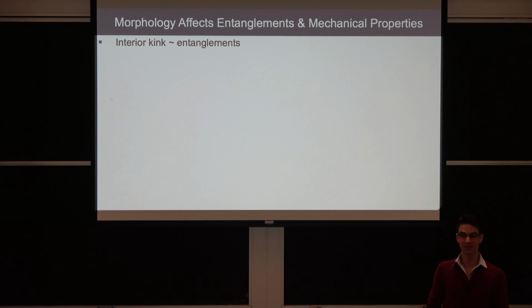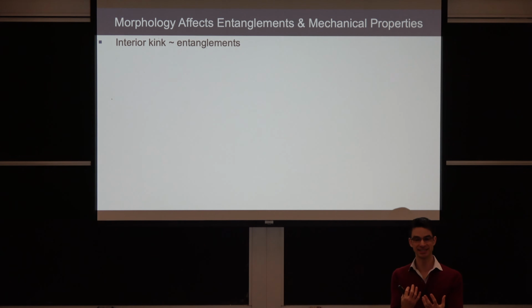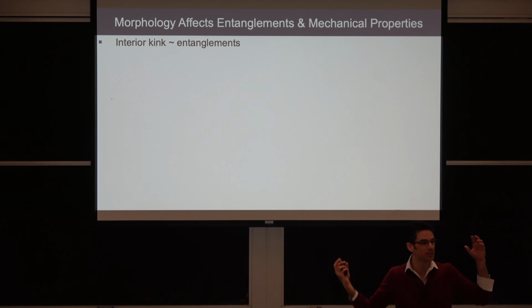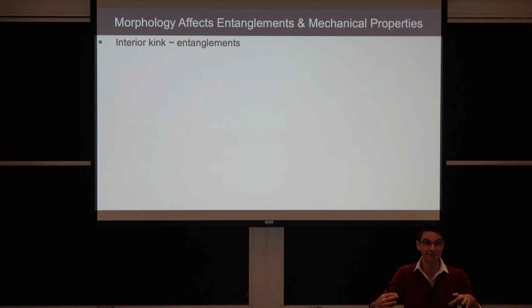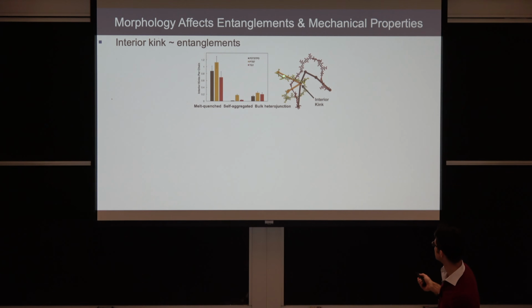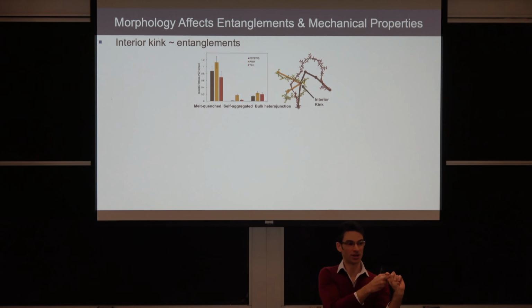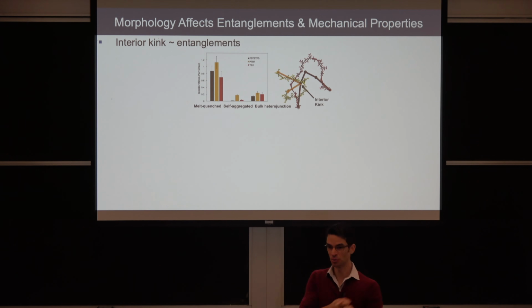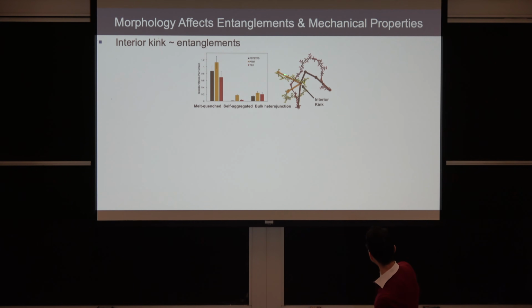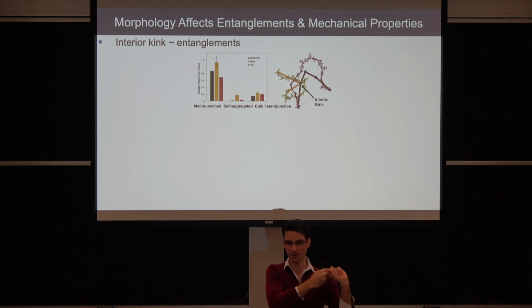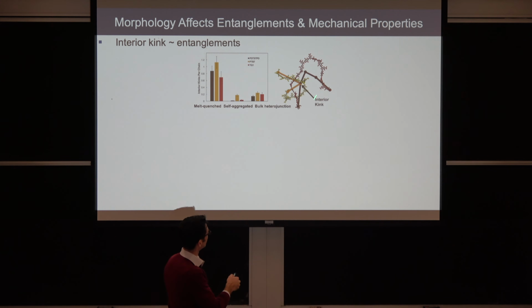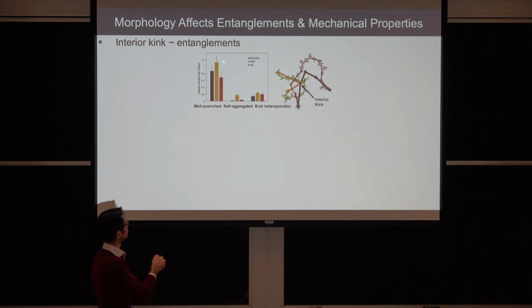All right, so another thing we can do that's really cool from these simulations is to calculate the number of entanglements. So you can really zoom in a way that you never would be able to experimentally. So you can zoom in and you can find these individual kinks in the chains where the polymer molecules are entangled. So if you plot these primitive paths of the molecules and you see where they intersect, that corresponds to where there's an interior kink. So you can go around, you can actually calculate where they are. And we can see that in the melt-quenched morphology, we have the most interior kinks.